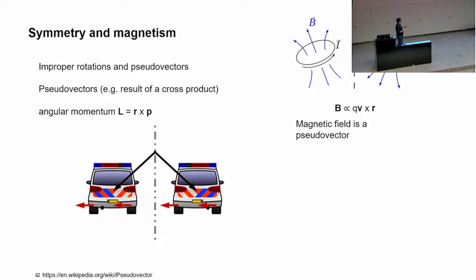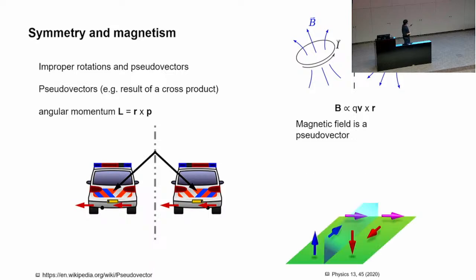Magnetic field is another of those things which behaves like a pseudo-vector, but I would like to come to the spin and magnetization. Here's a summary of how spin behaves upon a mirror operation. Imagine this thing in the middle here is the mirror plane. Now you see that when the spin is parallel to this mirror plane, it just flips its orientation, and if it's perpendicular to the mirror plane, it stays the same. This is a very special property which you have to know to understand how these symmetry operations work for magnetization, which behaves like a pseudo-vector.